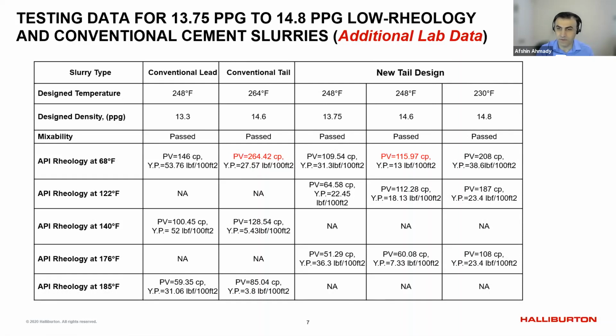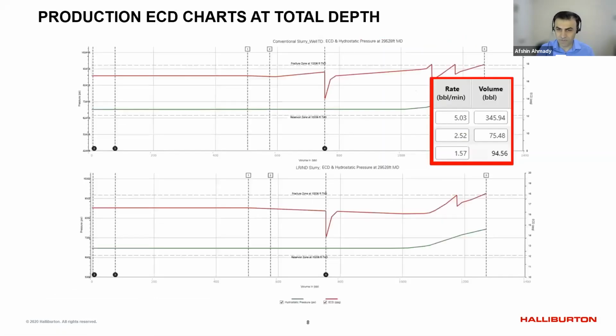drastically, and also we could change the cement density to even higher density and still having almost same ECD as original one. That was just for a special application when they had like high formation pressure. Simulation was used at its first step to see what's the impact of changing density as changing the rheology.